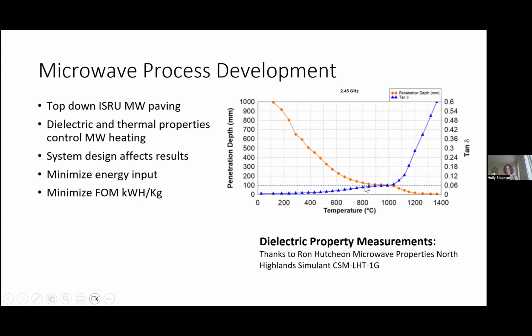And what I look for is a region where the penetration depth collapses, and the tan delta is at a level where, through much experience and a little bit of modeling, you're now in the zone for, in this case, softening the glass and vitrification. And yet this depth is still really good. So at 100 millimeters, that's the target that NASA gave me, at 4 inches. Okay, so, but we have to get it into this zone. And without getting into that zone, somewhere at 600, 700, 800, we're just wasting energy from the microwave.